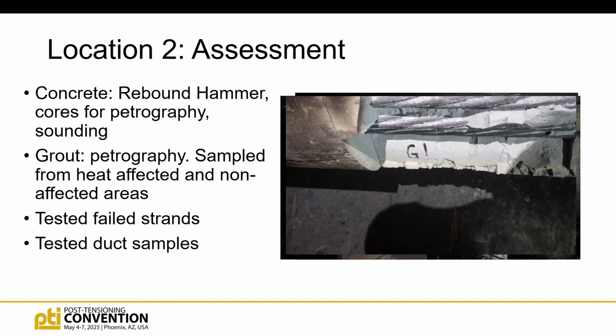And here's a shot of the strands and some of the grout we removed. We ended up sending 4 grout samples to our laboratory. 3 of the samples had been affected by the fire, and 1 was from a location unaffected by the fire so that we could do a comparison. And we had to do some additional testing of those samples to get a fingerprint on what that looked like. And I'll show you what that involves.